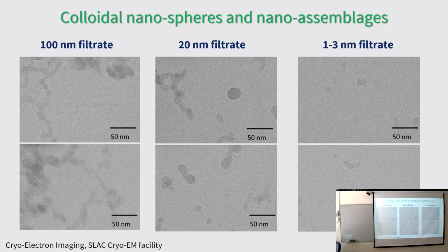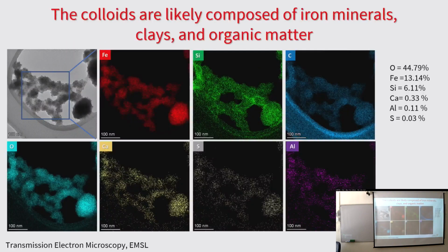This gave us some initial insight into the size and structure of the colloids, but we wanted to learn more about their composition. So we continued with transmission electron microscopy coupled with energy dispersive X-ray analysis to learn about the elemental distribution in our sample. On the upper left you see again this colloidal assemblage with multiple spheres making up the whole colloid. And then we detected high contribution of iron, silicon, oxygen, lower but still substantial levels of carbon and calcium, and also some contributions from sulfur and aluminum. These images suggest that our colloids are composed of iron minerals, clays, and organic matter, probably with bridging cations such as calcium. We were quite surprised by how high the oxygen levels were, because that suggests that we have iron oxyhydroxides present.